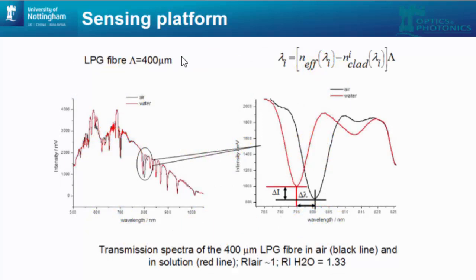The position of these attenuation bands in the transmission spectrum depends on the external refractive index, basically. So the refractive index of the cladding mode depends on the external refractive index, and by changing the external refractive index, as illustrated here, for instance from air to water, you see a wavelength shift and also an amplitude decrease. So you can use this to measure refractive index. Of course, this sensor is not selectively sensitive, so any change of refractive index will lead to a wavelength shift here.